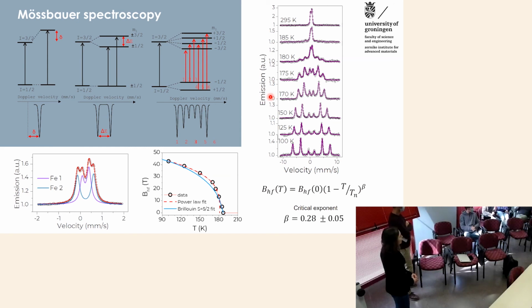It is a polycrystalline sample, but if you have a single crystal or film, whatever, then the ratio between intensities depends on the direction of the gamma rays with respect to the tensor that gives you the quadrupole splitting, which is the diagonal of the tensor. And in fact, here, for some reason, one of the components gives a similar intensity and the other a different intensity. In fact, this angle tells you the direction between the axial direction of the quadrupole splitting and the gamma ray. So I don't know in that case how it works, but in general.